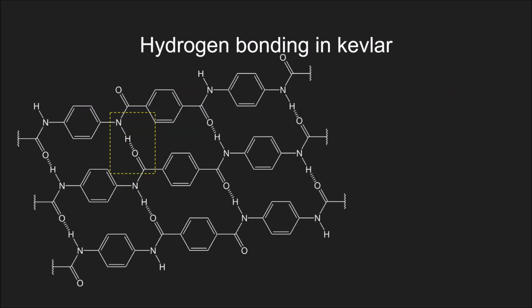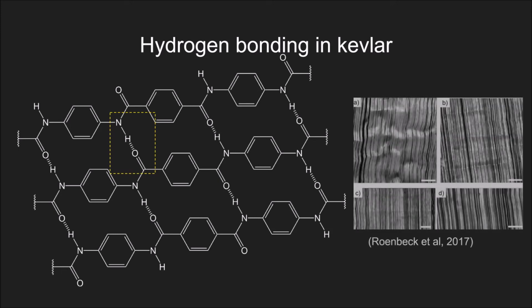We would expect to see hydrogen bonding between the amide groups of Kevlar like we saw in nylon. But unlike nylon, Kevlar has rigid benzene linkers between the amide bonds, instead of flexible linkers. This allows the strands to adopt a highly ordered microcrystalline structure, explaining its unique rigidity and strength. However, this actually presents problems for the manufacturing of Kevlar. Conventional methods, like heat or solvents, don't work to dissolve the fibers. Industrially, calcium chloride is used to disrupt the hydrogen bonding network to make Kevlar easier to process, but that must be removed in later steps.